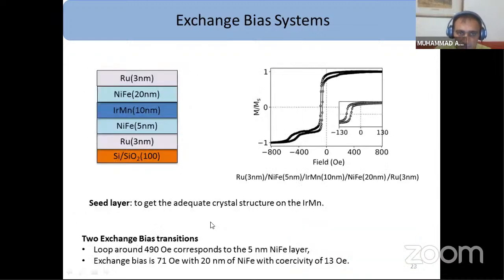The other exchange bias is seed layer based. Here I use a seed layer of nickel iron of 5 nanometers, and at the top of the structure we have a nickel iron. Because a ferromagnet ends at the top, we can use this for measuring the inverse spin Hall current. Here you can see this is the main exchange bias, and this effect is due to the seed layer. Here you can see 5 nanometers of seed layer. The seed layer is used to get the adequate crystal structure on the iridium manganese.